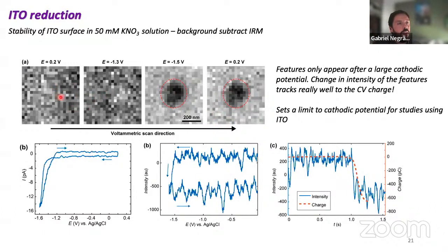So those are the images. You can see that I have absolutely nothing until we get to very negative potentials, and a feature appears. Even if I flip the potential, the feature is still there. So pretty much it's a nanoparticle that forms and that I cannot reverse. And we can track the intensity of this optical feature together with the charge that I can integrate from the CV. It's quite nice to see that I can correlate those two factors, and it gives us a visualization of a chemical reaction happening here. That gives us a lot of confidence that we can use this technique to map chemical compositions and chemical gradients and to investigate reactions.